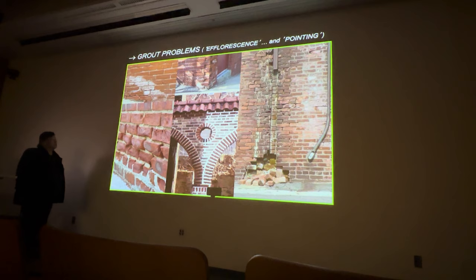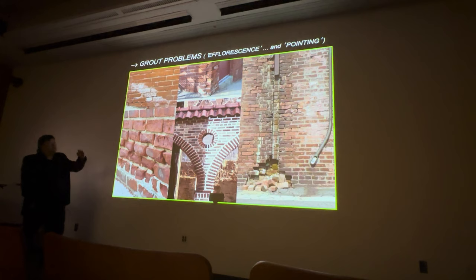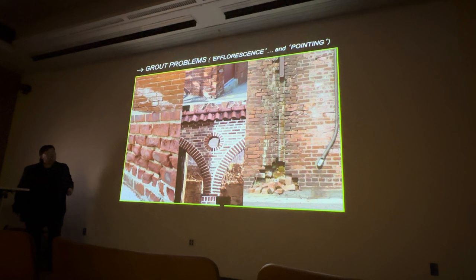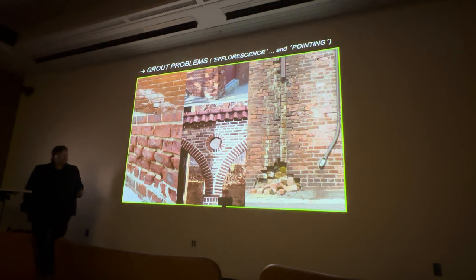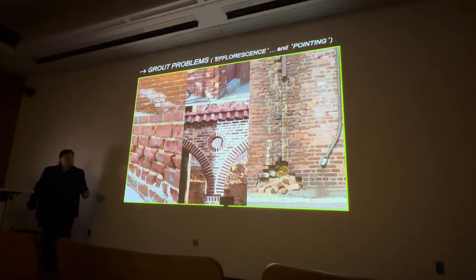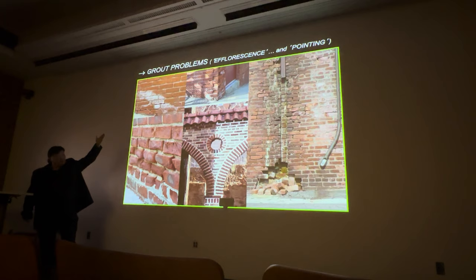Spalling means the water is leaking into it. Probably there is moisture inside that freezes and pushes the wall. That consideration is also for a corner, also a lower part of your brick wall. So you need to seriously consider repointing and fixing this quickly before it collapses. This one we know, the water is basically just draining through it and making a big mess. The entire wall needs to be repointed.